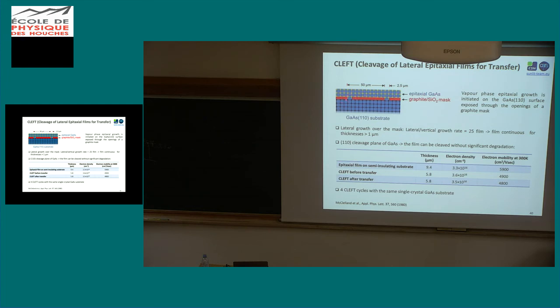What happens is that the gallium arsenide, or something that is lattice matched, right, will start to nucleate in the opening here, and then you proceed with epitaxy that is called lateral epitaxy. Basically, the crystal is sliding on top of this low surface energy graphite mask, and since it's not really touching, or only has some van der Waals bonding with the graphite mask, whenever the two crystals join, they will join perfectly. So they demonstrated that you can actually have excellent gallium arsenide films.